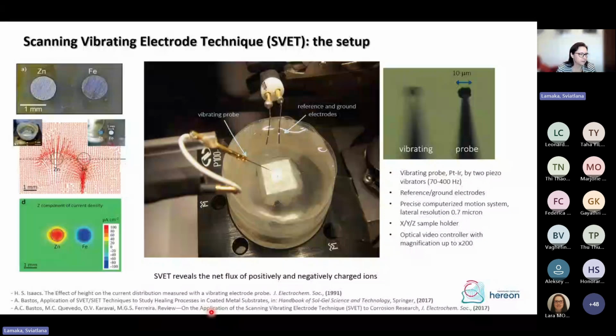This is a typical setup with a vibrating probe, and vibration piezo elements are located in this part of the vibration head, along with reference and ground electrodes. Typically, the vibration probe is platinum iridium. We use commercial microprobes; there are several suppliers for this. And this is a platinum iridium microprobe with only the apex of the tip not insulated.